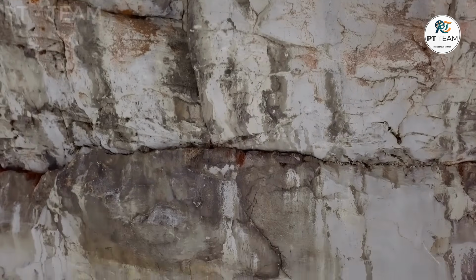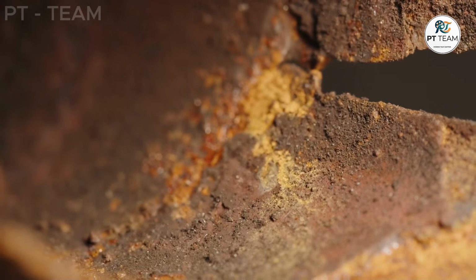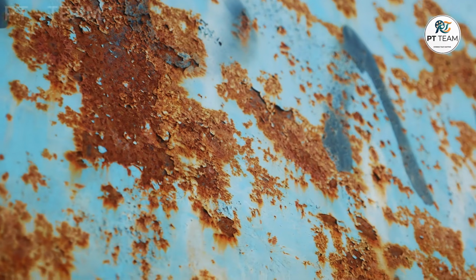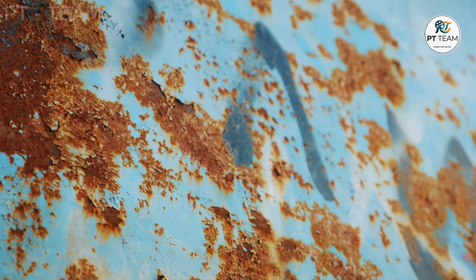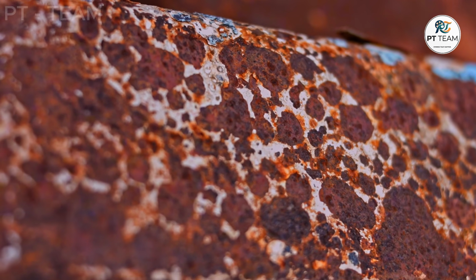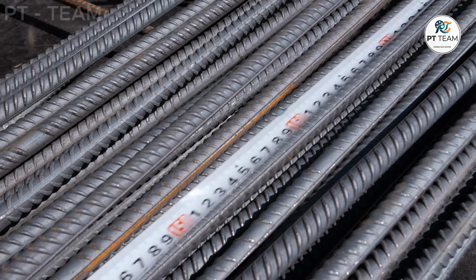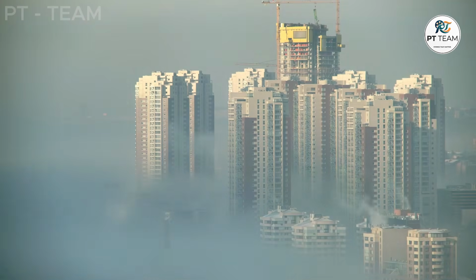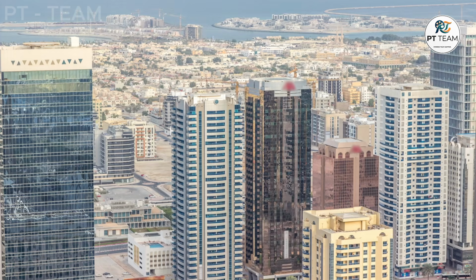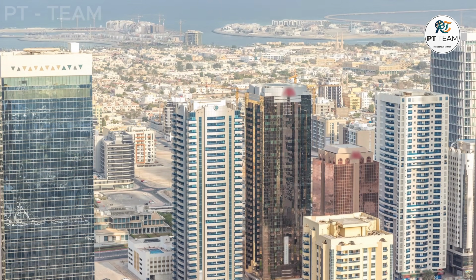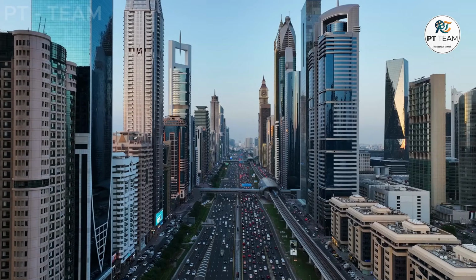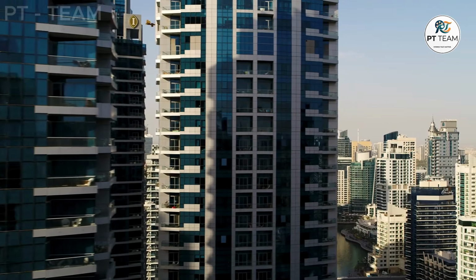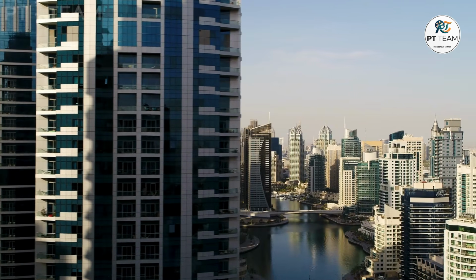The moisture trapped inside the microscopic pores of the concrete serves as the perfect electrolyte to keep this destructive circuit running. As the steel dissolves, it creates corrosion products, which we commonly call rust. The terrifying part of this chemical reaction is that rust occupies a significantly larger volume than the original steel. As the rust continuously accumulates along the boundary between the metal and the concrete, it generates a massive amount of outward pressure. This incredible internal pressure eventually overcomes the tensile strength of the concrete itself.